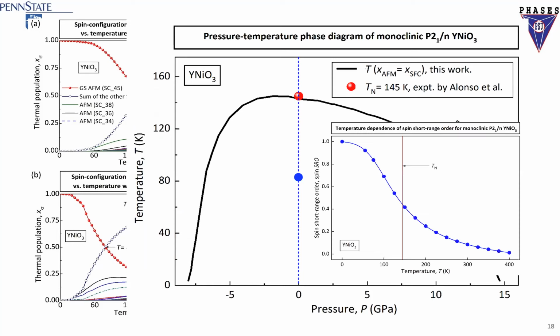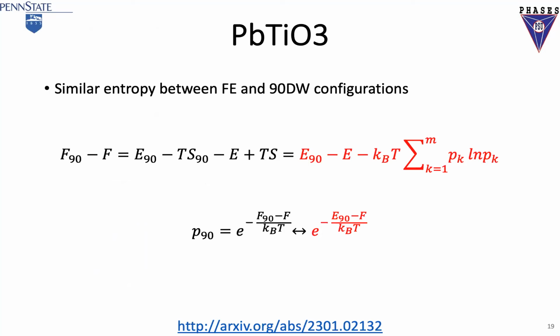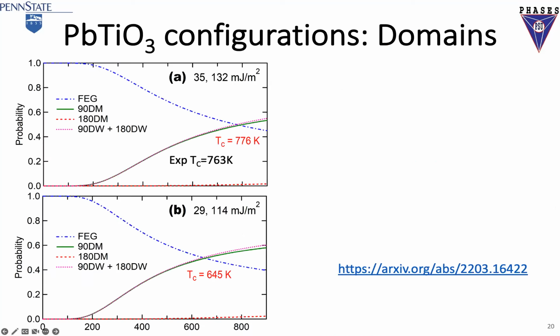All right. So I have to go back to the titanate, right? The titanate will have 3 configurations. Turned out, as shown by Karin's MD simulation, entropies are very close. That means we don't need entropy in this case. So take Helmholtz free energy as energy at the domain wall, we can actually calculate. We can then mathematically show that the entropy effect is very small if the entropies of different configurations are the same or similar. So we take that together. We just put it into our model.